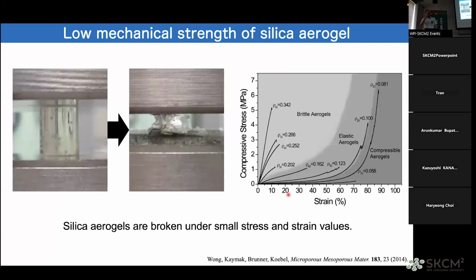But as I said, the silica aerogels are mechanically very weak. So this is a picture before silica aerogel is compressed. And during the compression, the breaking typically starts at 10% compression or 10 to 15% of compression. So this is an easily breakable material.